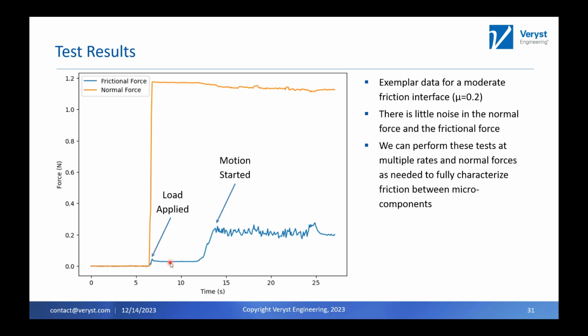You see a little jump in the frictional force measurement as well, which makes sense. There might be a little angle on there. And then we'll say 5 to 10 seconds later, we actually start the machine. We start it moving. So you see the friction force increases, and then we get stick slip. And then we went here for, we'll call it, 10 to 15 seconds. And then we could extract the normal force from that, right?